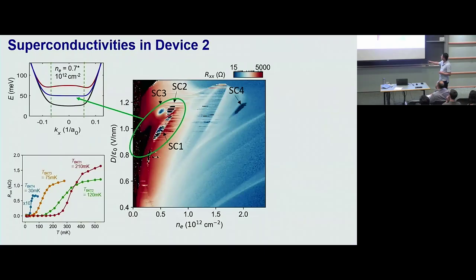Number one thing, the Tc of these 4 states are like this, okay? The 2 smooth ones have relatively lower Tc, and the 2 jumpy ones, when they are not jumping, you can measure the temperature dependence, and they have relatively higher critical temperature.